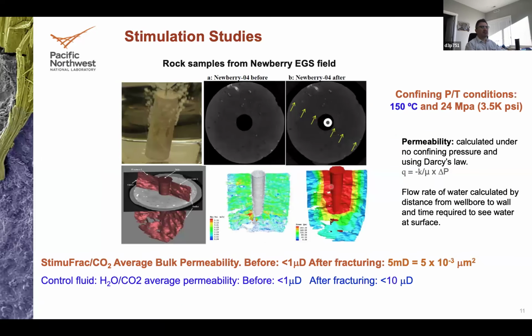So what we see is consistently, particularly with StimuFrac CO2, very high increases in permeability, or fracture permeability in this case, of the fractures generated by StimuFrac CO2 at 150 Celsius and 3,500 psi. We always generate this kind of planar fractures, parallel to the wellbore direction.